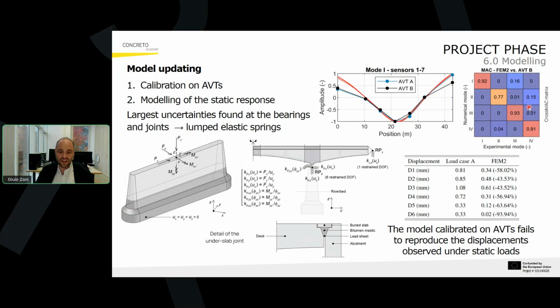You see that we were able to calibrate the numerical model on these measurements, which is something generally done, but also to validate this model on the load test which we performed with this heavy goods vehicle. And we realized that the model calibrated on the ambient vibration test fails to reproduce the displacement observed under static load. This has to do with existing structures in which we might have some friction effects at the supports, and some nonlinear behavior at the joints.